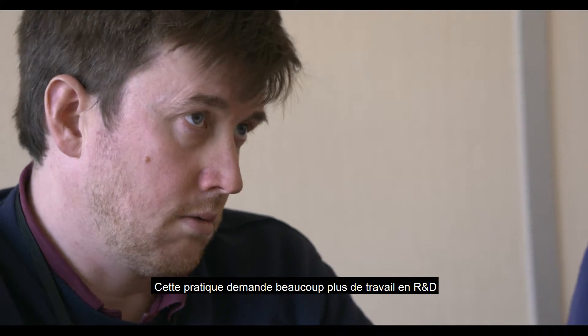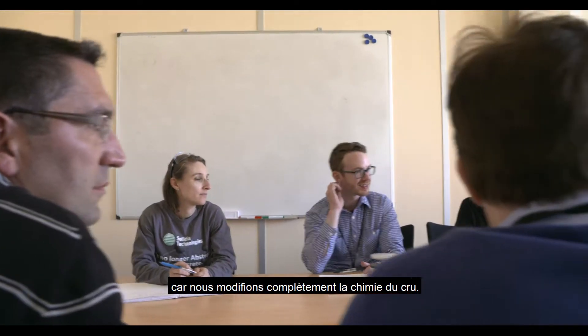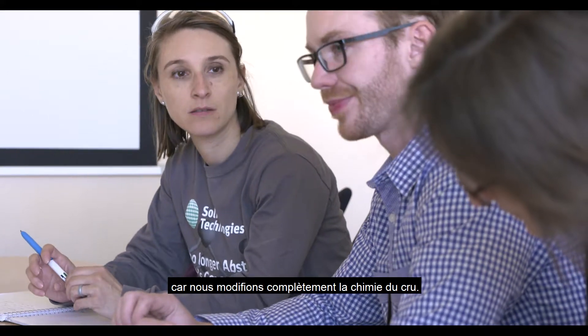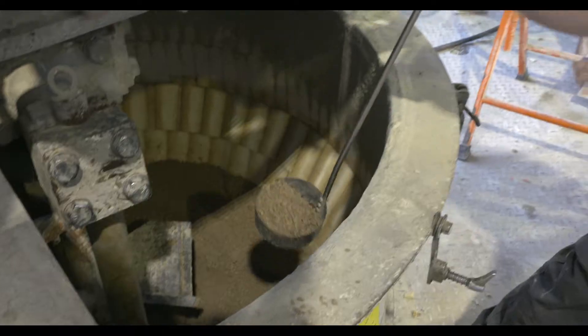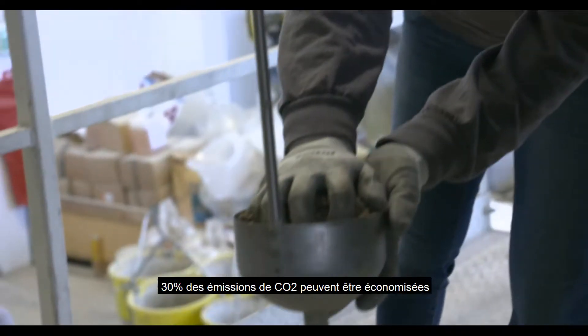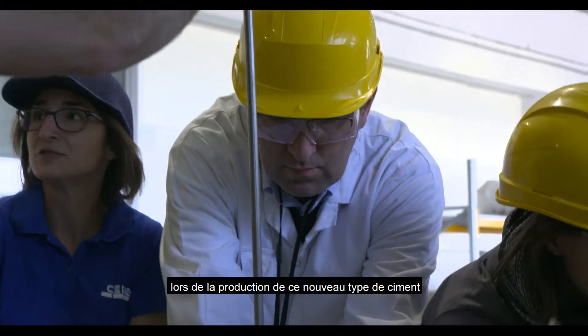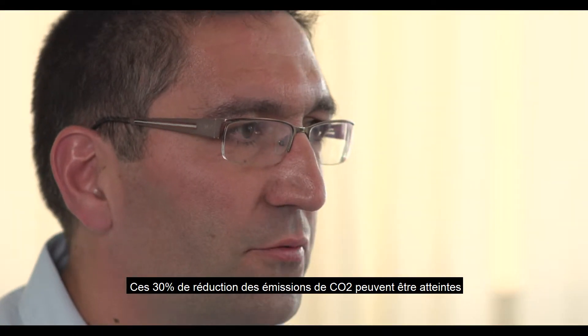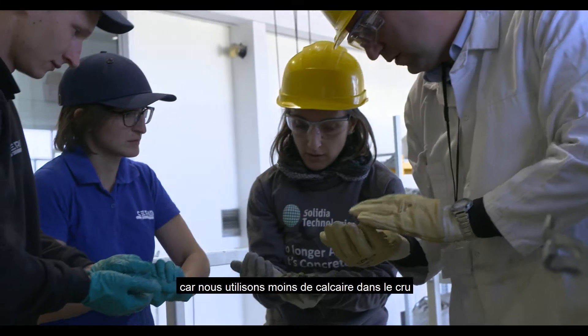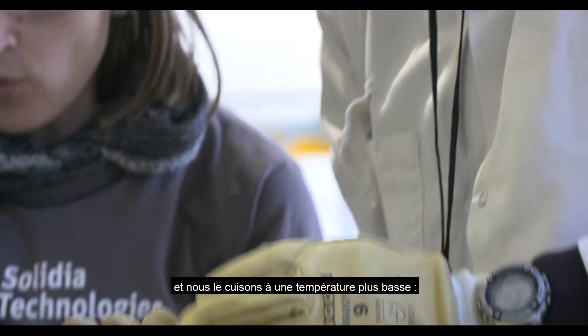These last levers demand much more R&D efforts because we are completely modifying the chemistry of the raw mixes. Solidia cement presents an alternative to our existing cements — 30% of CO2 emissions can be saved during the production of this new type of cement in our cement plants, because we use less limestone in the raw mix and we clinker it at a lower temperature.